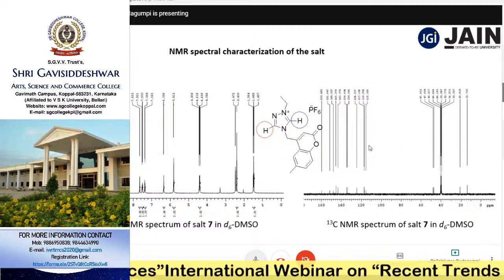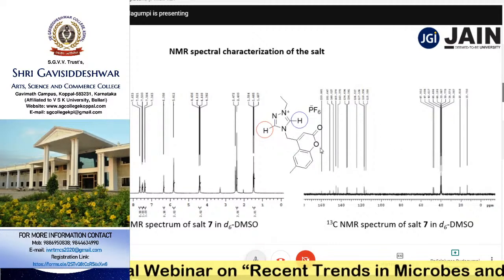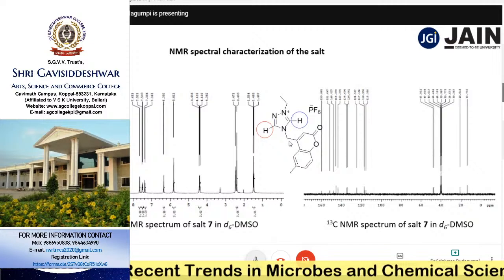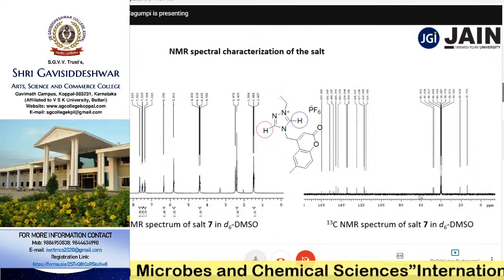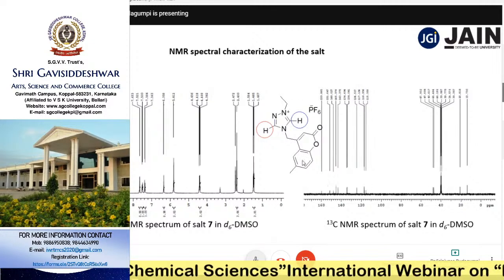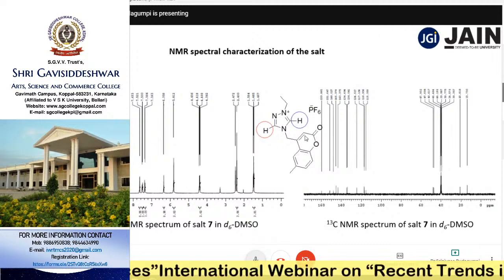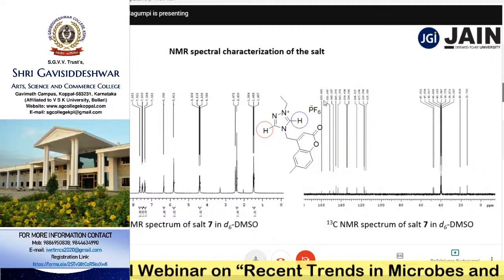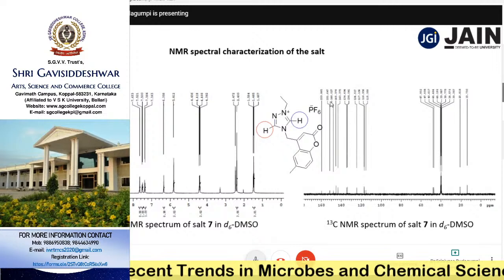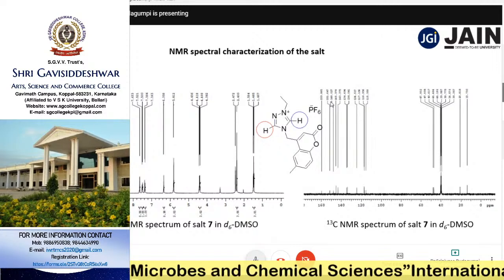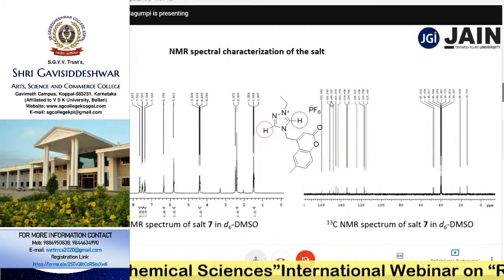Similarly, carbon NMR is also recorded for this particular salt. This has 4 alkyl substitutions. One is here, second, third, and fourth. These are the 4 alkyl substitutions, while the rest are the aromatic carbons, in which coumarin has signature peaks around 160, 150, and 148. So this is evidence that the salt has been formed.